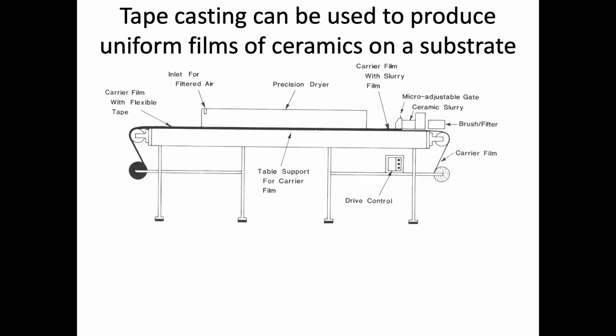All right. So another technique that is used is tape casting. And so this is where we start to get into what I would probably say are the more specialized applications. So tape casting is called that because we're forming a tape or a film. And so this is kind of what a typical setup would look like for tape casting. And what this gives us is the ability to form these very uniform films of a ceramic onto a given substrate that we have. So this could be a flexible substrate or tape. It could be something else, but it gives us a thin film on some type of carrier substrate.